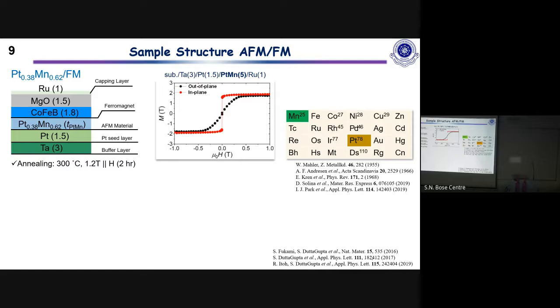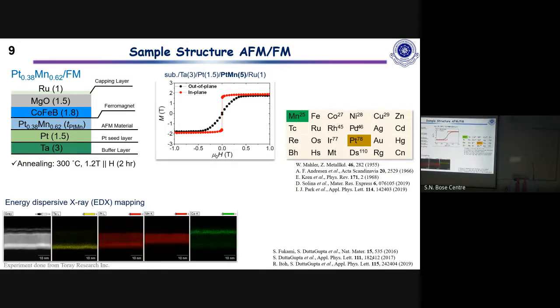And this is a magnetization versus field at room temperature, where the black line is the data when you apply the magnetic field out of the plane, in this direction, and the red one is applied along the plane, which is this direction. So from here you can see that the easy axis is in the plane, and you also can get the anisotropy field roughly from this point. And we also did some more characterization, for instance, the energy dispersive X-ray mapping to see that there is no significant intermixing or interdiffusion of the different layers. So here you can see the elemental mapping of tantalum, platinum, manganese, and cobalt. So you see that there is no significant diffusion between any one of the layers.